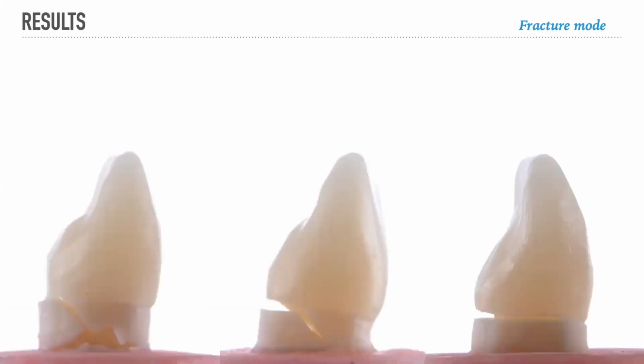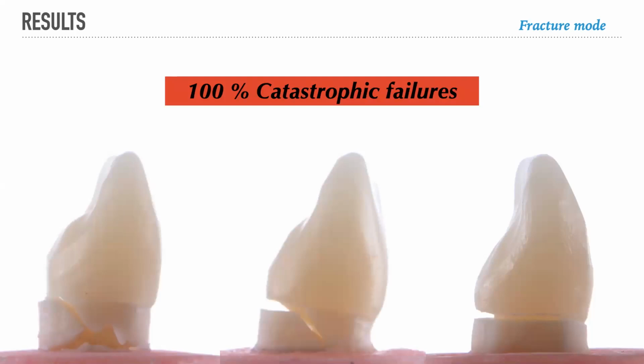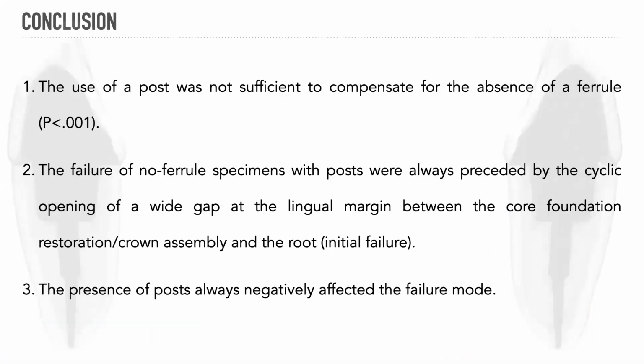But the problem is, in this study, we found 100% of catastrophic failures because all the samples have intracanal posts. So all the samples presented glass fiber posts or titanium posts. So all of them present 100% catastrophic failures. So the conclusion of this second study was that the use of posts was not sufficient to compensate for the absence of ferrule, because we had a difference between the ferrule and the non-ferrule groups. The failure of the non-ferrule specimens was always preceded by the cyclic opening of a wide gap at the lingual margin that we call initial failure, and the presence of the post always negatively affected the failure mode.